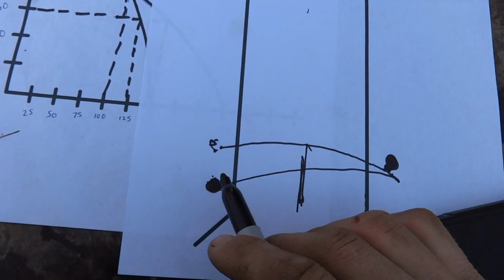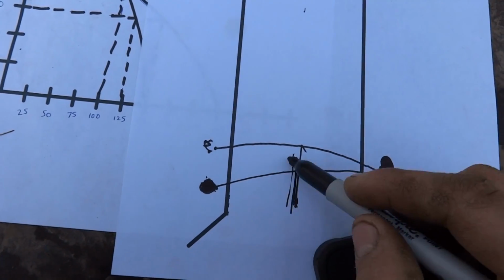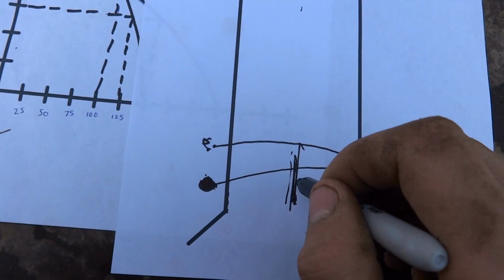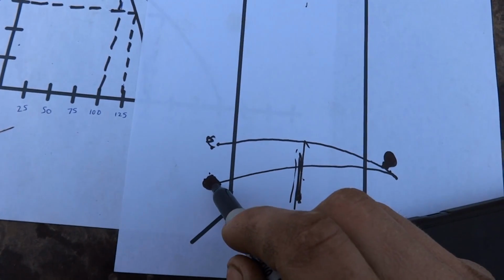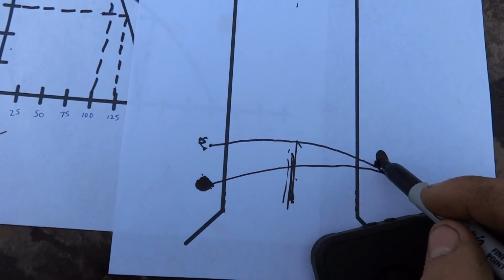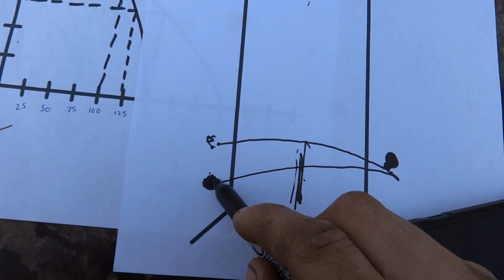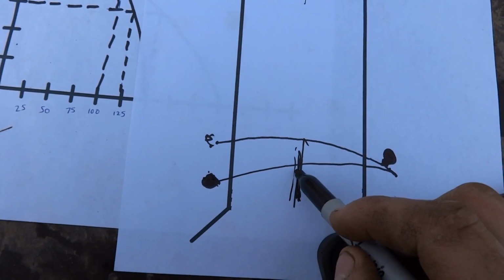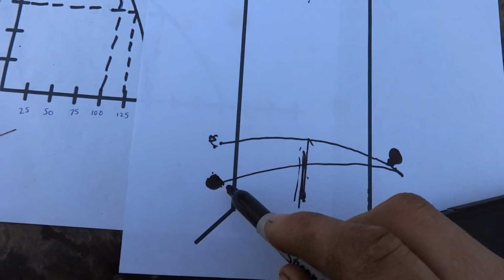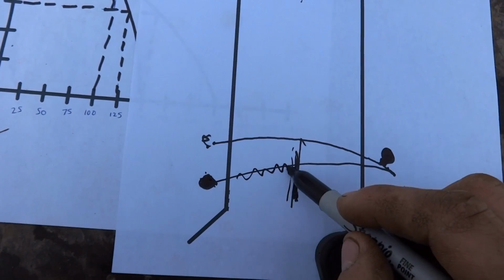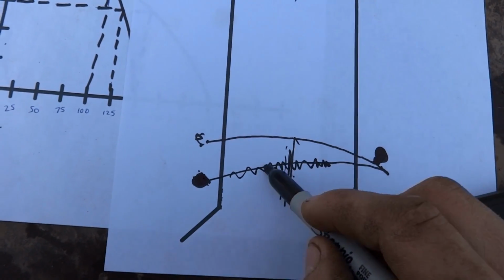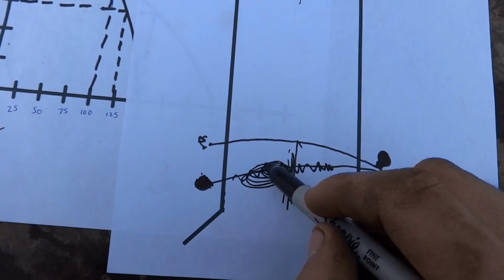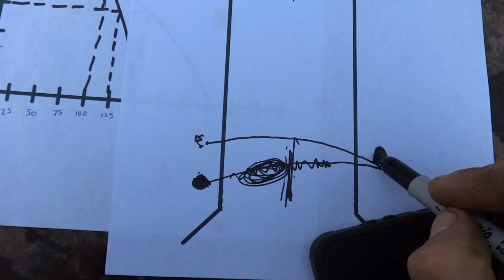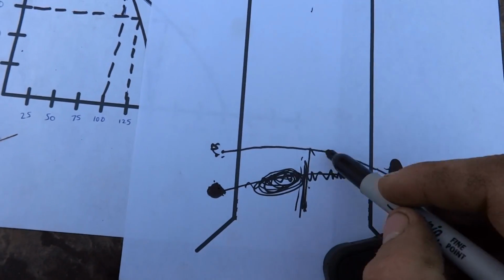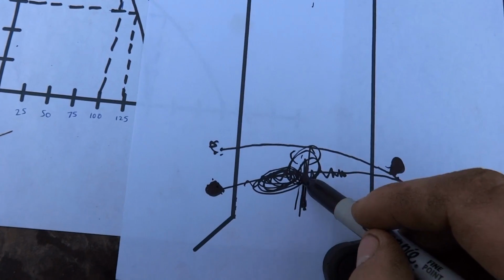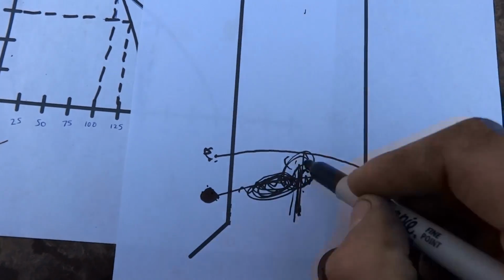that is more liquid, a high chance of blowing a hole in the middle of the pipe because that's where all the heat collects, because it's not solidifying over here, and the heat kind of sort of follows you to the right hand side, but it still hasn't solidified fully on the left hand side, so all the heat is going to collect in the middle here. You move from the right hand side over to the left hand side. This left hand side hasn't solidified. The heat is kind of sort of following you, but the puddle hasn't solidified fully yet. You move from right hand side back over to the left hand side. It's just tossing more heat into the middle here. You're going to blow a hole in the middle there because you have so much heat in the puddle.